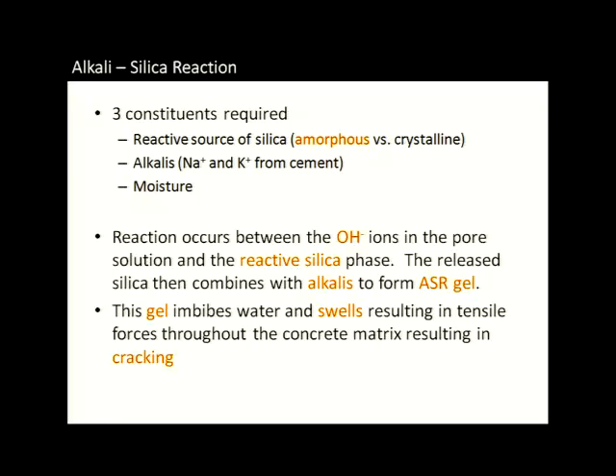It's hygroscopic. It wants to pull water into it. As it does that, the gel expands. As it expands around the surface of aggregate and in microcracks in the aggregate, it actually creates enough tensile force, or can create enough tensile force, to actually break the concrete apart. So the outward manifestation that you get from alkali-silica reaction is an expansion. So you'll see a lot of the slides that I show later on, we're measuring expansion for concrete that we've either cast in the lab or we've taken from the field. And if that expansion is great enough, you get an outward manifestation of cracking on the structure.